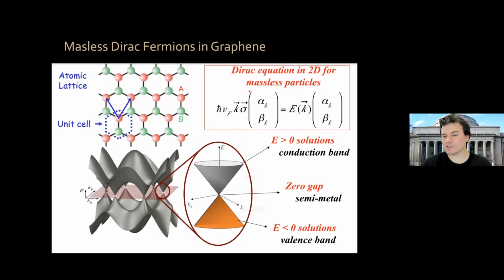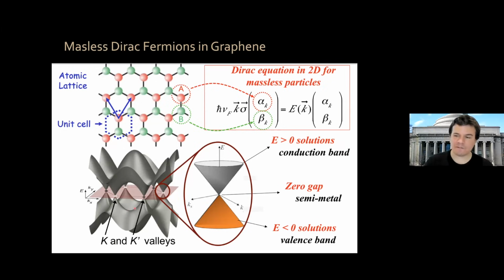Now in the Dirac equation, this is a spinor, which typically tells you whether the spin of the electron is up or down. Here in graphene, this is a pseudo spin, a pseudo-spinor, which tells you whether the electron wave function is on the A type of sublattice or on the B type of sublattice, okay? Now, the only other thing that I need you to remember from graphene is that there are 2 independent valleys, or these Dirac cones, we call them valleys. They're called the K and the K prime valleys. So electrons in graphene have this 4-fold degeneracy, spin up and spin down, valley K and valley K prime. Just remember the number 4. It will appear later in the talk, okay?